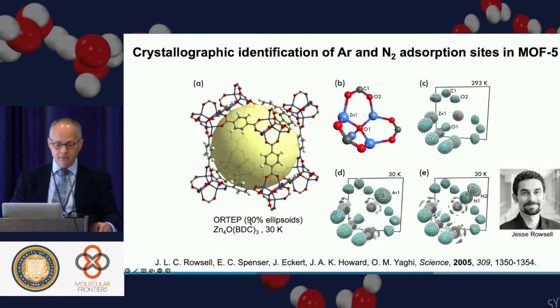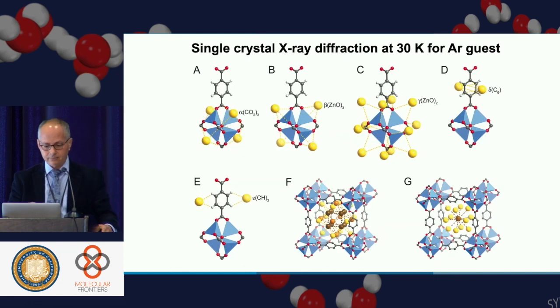And you see here, for the inorganic chemist, these are 90% ellipsoids. This is a crystal structure, very well behaved, and proves beyond doubt that your structure is open and does not collapse in the absence of stuffing or of guests. But then what this student did, which was really a great experiment, was to dose the crystal with very tiny amounts of argon and, in another experiment, dinitrogen. The object here was we wanted to identify what the adsorptive sites are. Where does nitrogen bind? Where does argon bind when it's introduced in the structure? And it turns out, I'm showing the results here for argon, but for nitrogen it's very similar.